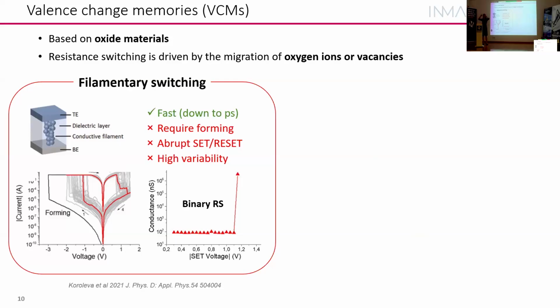So there are mainly two types of valence change memories, resistive switching devices, with two different mechanisms. The most common one in literature and in industrial applications is the filamentary switching. This means that the device is in the off state, high resistance, and to make it work, first you have to apply a very high voltage. So here we see what is called the forming voltage. And what we normally think is formed here is a filament of oxygen vacancies, which connects one electrode with the other. These types of devices are very fast, but they have some drawbacks. So you need this high energy for the forming.